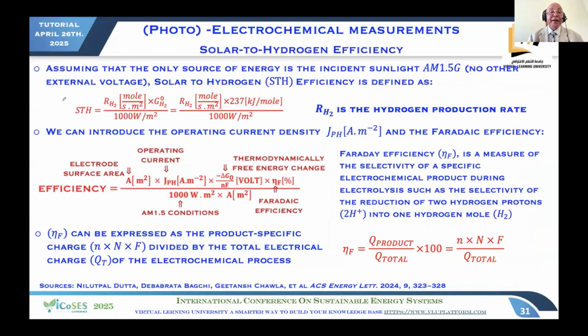So that's how you can calculate or measure the efficiency of hydrogen production. This 19% that Thomas Hannappel showed you yesterday is measured like this. You have the rate of hydrogen production here, this number here, and this you can measure with mass spectroscopy, for example. You have this free energy here, this is delta G, not G. And that's divided by the AM 1.5 power in watt per square meter. That's the solar spectrum, and that's the efficiency solar to hydrogen. So again here, written very explicitly: that's the rate which you can measure, that's the value, the minimum energy you need for water splitting, and here is the AM 1.5.